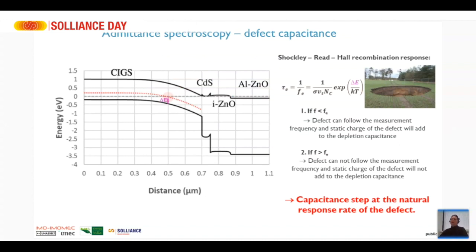When we introduce bulk defects in the CIGS layer — represented here as the red line — these defects typically show up as energy states within the band gap of the semiconductor. Within the forbidden band there are normally no electronic states, but defects create energy levels within the band gap. These energy levels act as very strong recombination centers and degrade the efficiency of the solar cell. Those are exactly the ones we want to eliminate.